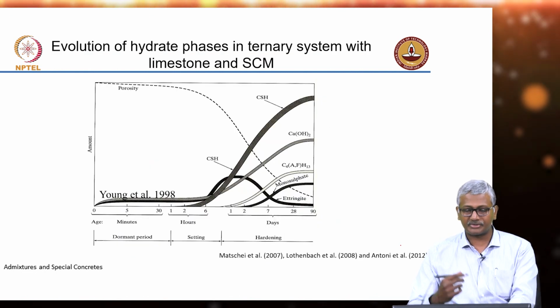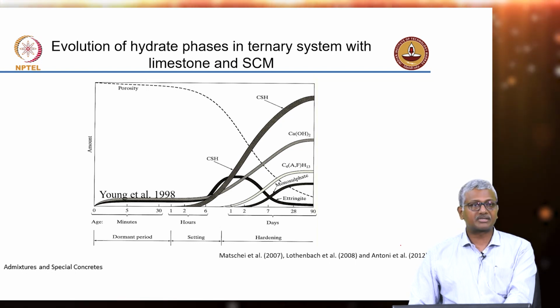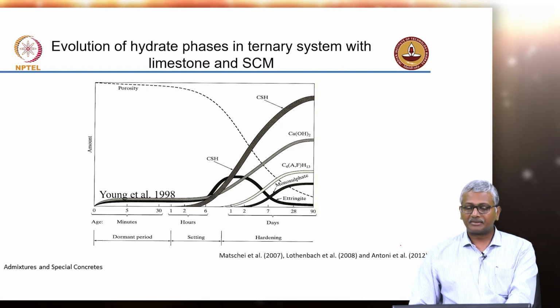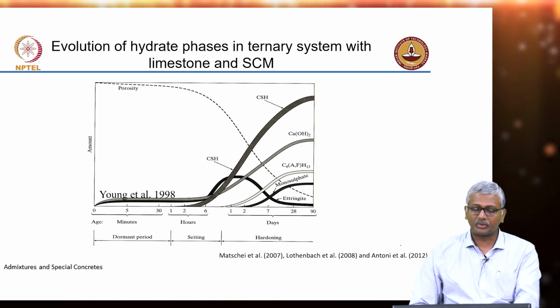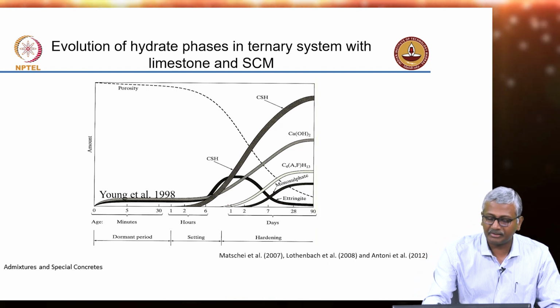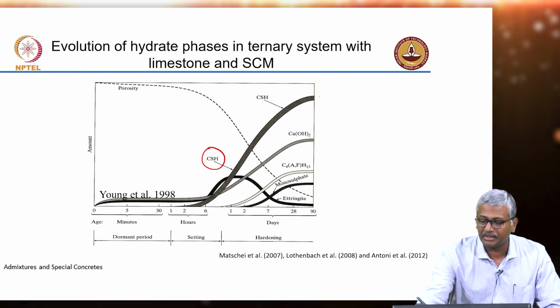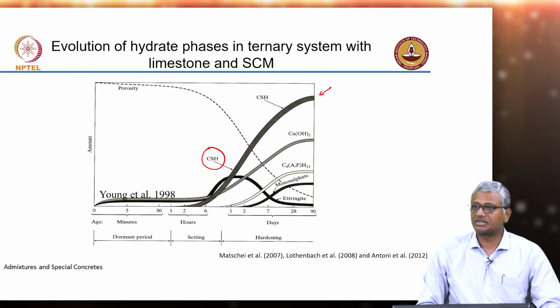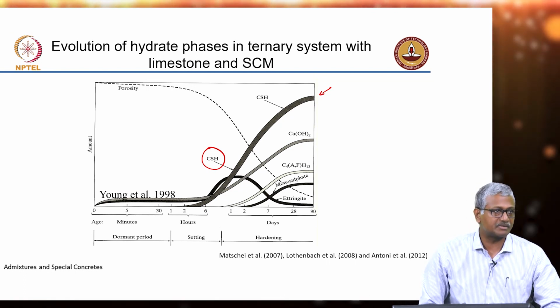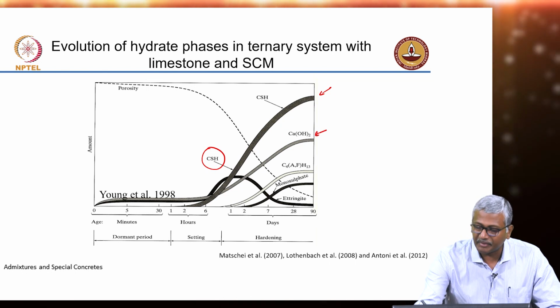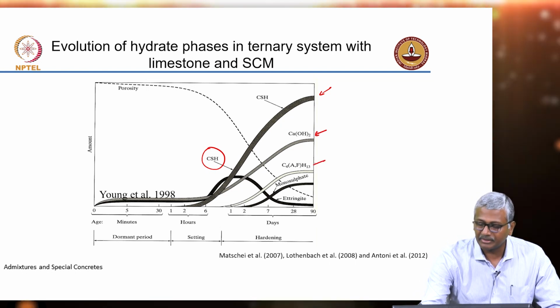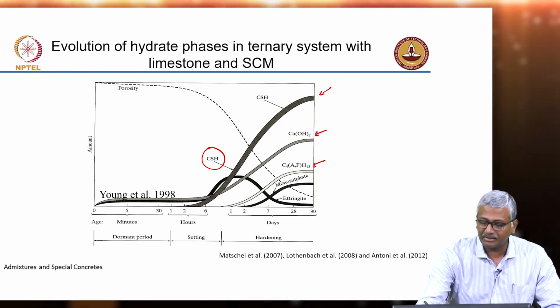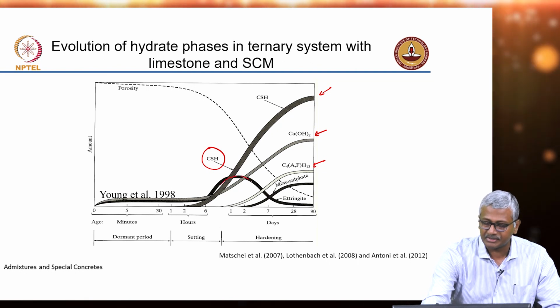So, I will just talk about this with respect to how products evolve in a cementitious system. This is a typical Portland cement. We know that beyond a certain period of hydration, CSH starts forming rapidly. In the long term, CSH occupies the most volume inside cement paste. We have next calcium hydroxide, then we have calcium aluminate hydrate, and ettringite that starts forming in the early stages decomposes to give rise to monosulfate.